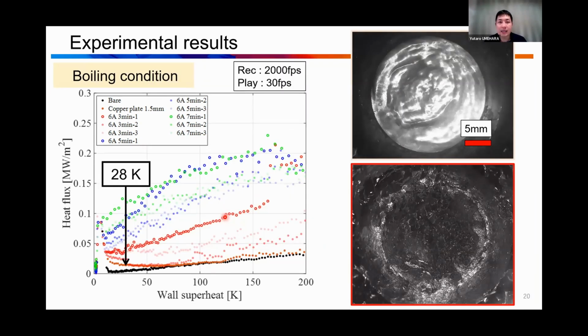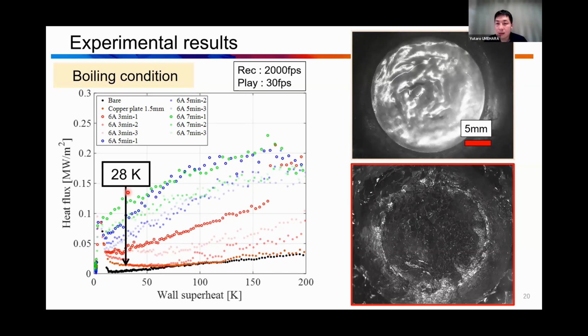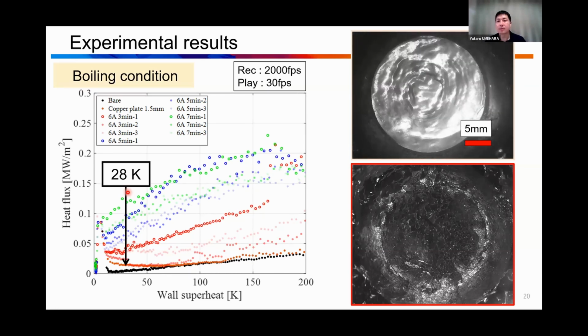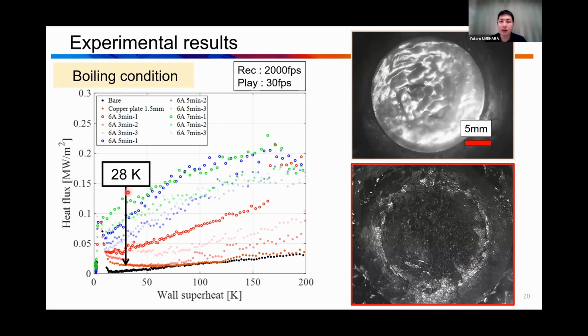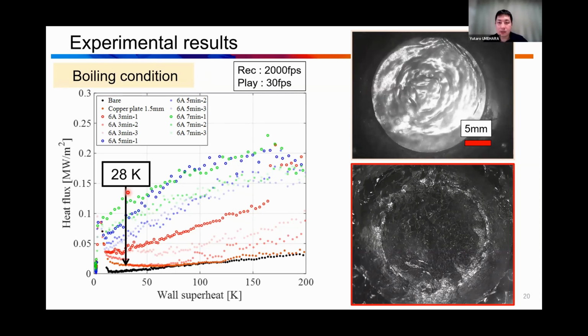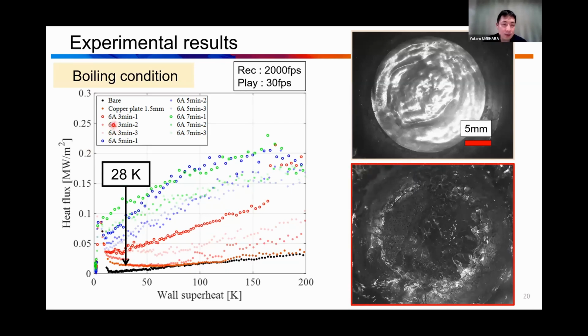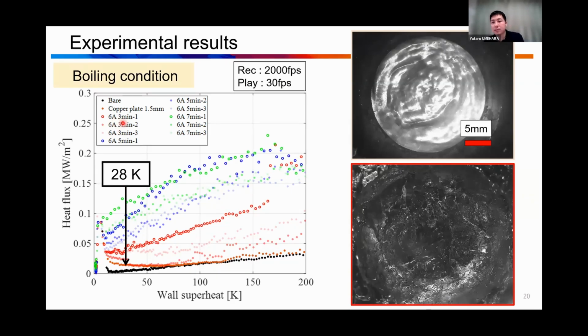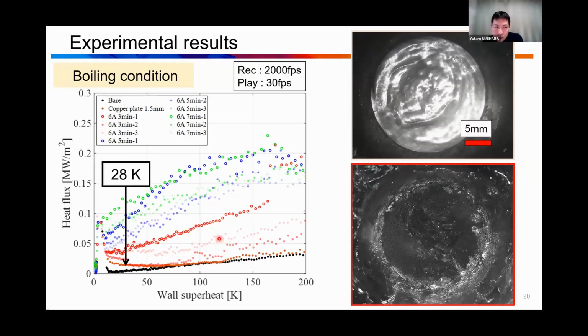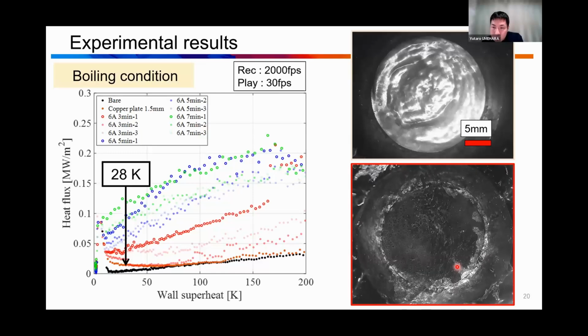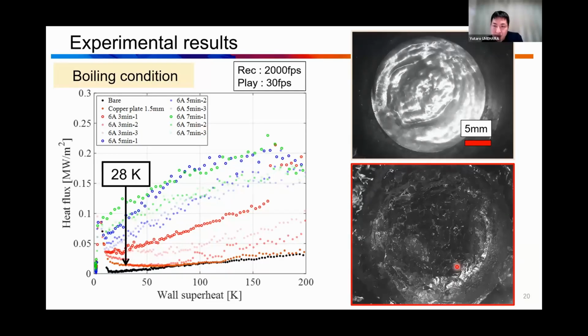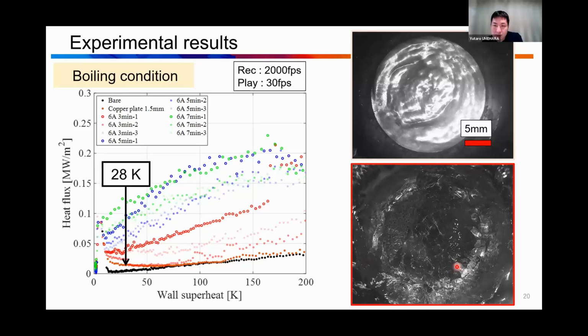Okay, the next one is a high-speed image during the quenching. This one is just the copper plate at around 28 Kelvin. Please see. It's like this: a very smooth film boiling, and the vapor film covers the whole surface. The next one is 6 ampere, 3 minutes deposition of the copper spray. It's like this, at the 28 Kelvin point. So there is no smooth vapor film. We cannot see any smooth vapor film.